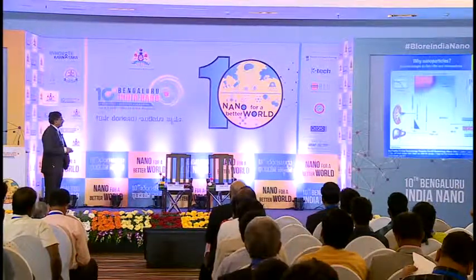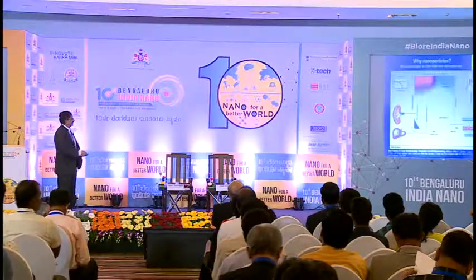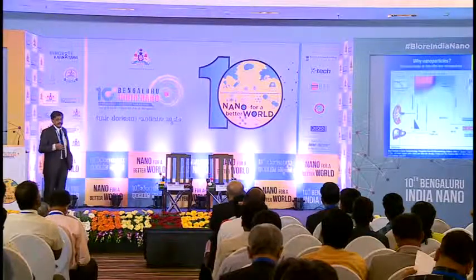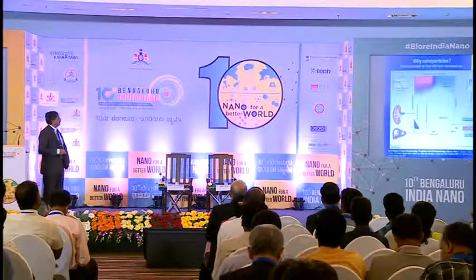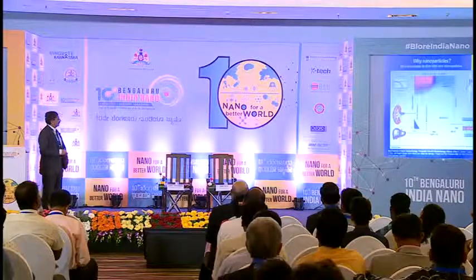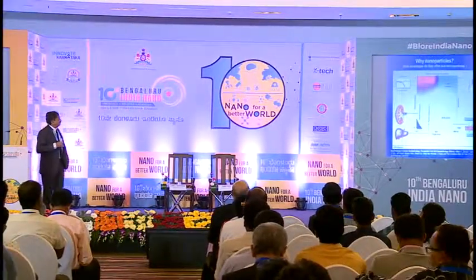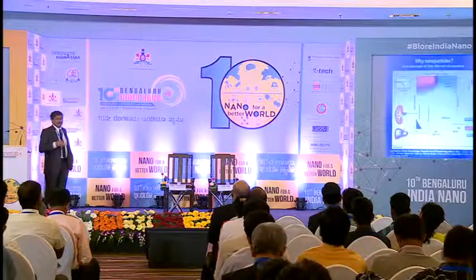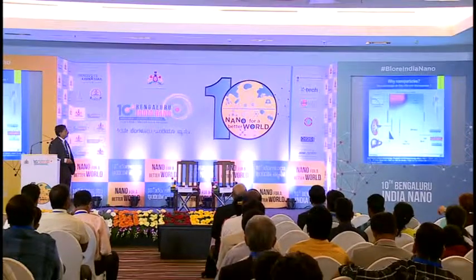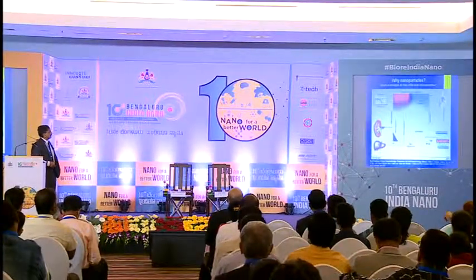At the lower end of the scale, less than about 10 nanometers, it's interesting. The 100 to 200 nm particles accumulate in rapidly dividing tissue but also in the liver and the spleen — that's unavoidable. We can make use of that liver concentration, as I'll show later. In the smaller size range, particles are cleared by the kidney, so they don't accumulate in liver and spleen. There is work spearheaded by Cornell University researchers — Cornell dots — looking at better biodistribution in lesions using the small size.